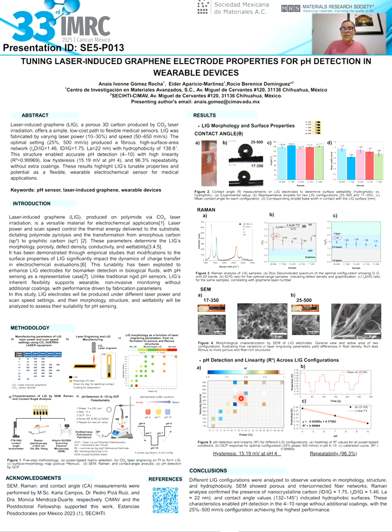Finally, pH detection was evaluated for all configurations that adhere to the substrate. In figure 5a, the R-squared values are shown, with the best performance obtained at 25% power and 500 millimeters per second. Five samples per configuration were used to ensure repeatability. For this configuration, the linearity was very high, R-squared is 0.99, and the slope was 20.95 millivolts per pH, representing the sensitivity.